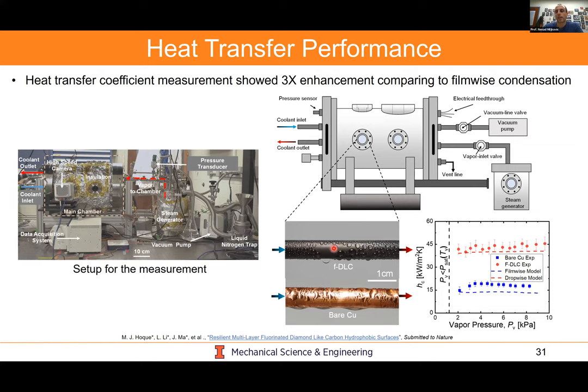And you can see on the right here, the condensation heat transfer coefficient as a function of vapor pressure and comparison with theory for both experiments. And we get good agreement with theory and what we expect. So the coating itself is exceptional in terms of the heat transfer performance. It's not degrading the heat transfer.